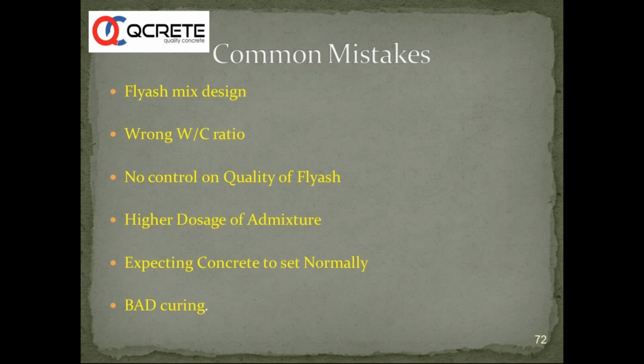We need to also remember that 1 kg of OPC in terms of strength contribution is greater than 1 kg of fly ash. So 1 kg of fly ash will not give similar strength contribution in a concrete mix when compared to 1 kg OPC. So we need to be aware of that one. So the most important point, as I said, when you are using OPC fly ash mixes or any SCM for that matter, we need to reduce the water cement ratio as much as possible to make it a candidate for making higher strength actually. If you want to make a higher strength or equal strength, you need to use the potential of water reduction. You need to reduce the water cement ratio as much as possible.